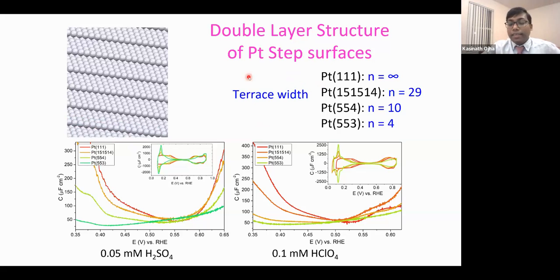Yeah, okay, Dr. Kashinath. So then what we did, looking at the double layer structure, is we changed the surface. We introduce step sites, and we want to see how those step sites affect the double layer capacitance of the platinum. This is a typical stepped platinum crystal, and you have what we call terraces, and this position we call a step. So we have steps and terraces, and we can change the width of the terrace depending on the crystal. We have different crystals, with this n value indicating the number of terrace atoms.